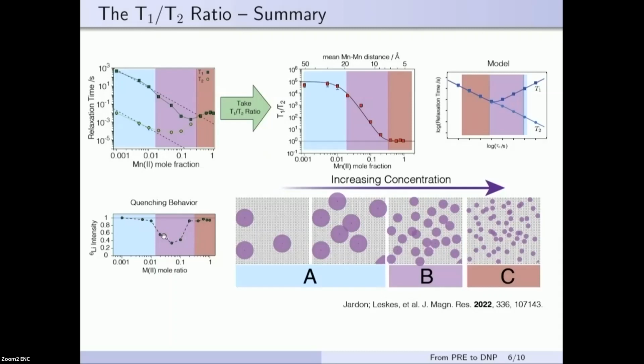But then we enter this regime where the relaxation time starts becoming shorter. If we go back to the BPP model, it's like moving from the right to the left. So for a fixed distance, the T2 of a given nucleus will start increasing. This is equivalent to the quenching radius becoming smaller and smaller. At some point, this shrinking is more important than the increase in the number of spheres, and this is the point where the quenching inverts. Then at some point, the radius of these spheres is so small that we are able to observe nuclei in nearest neighbors to the paramagnetic center.